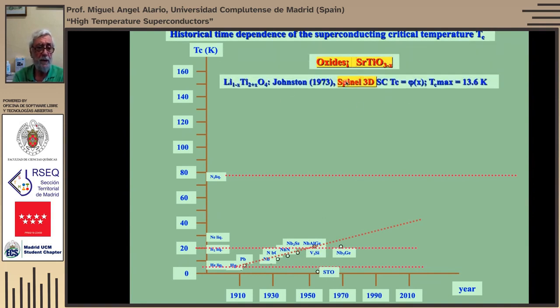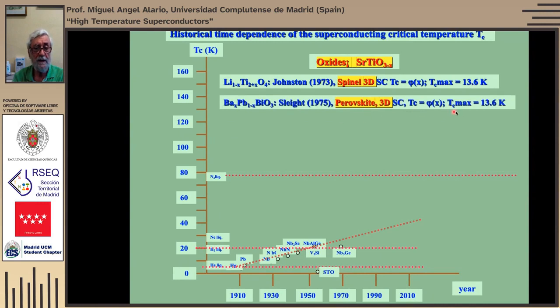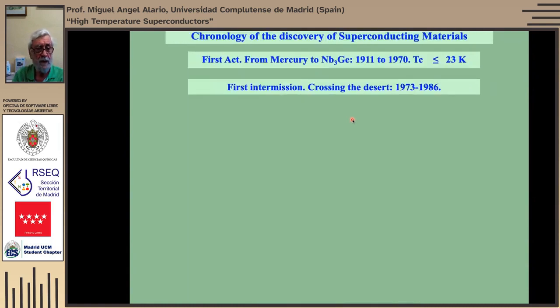But then, at that time, a spinel was found, this interesting compound, with 13 Kelvin, and another perovskite also the same. So in this period, two more materials were found. They're not very high temperature, but two interesting structures. Spinel is very well known, and perovskite even more. It's the most important structure in solid state physics and chemistry. Anyway, Matthias was out of touch with reality. Predictions are difficult, so we should not make many predictions.